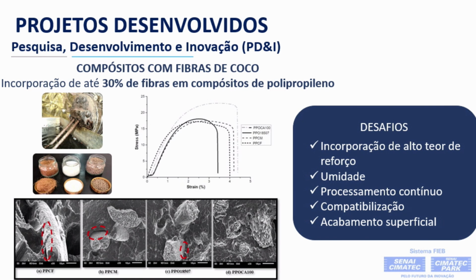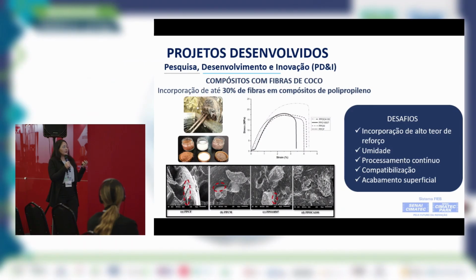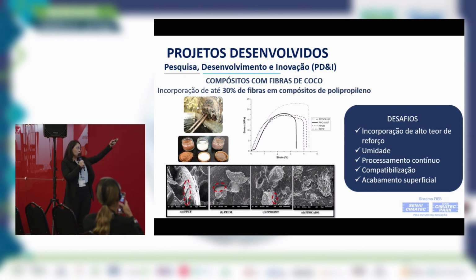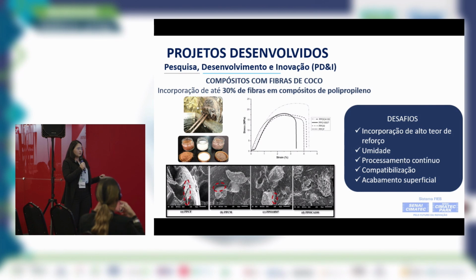Let me talk about the projects that have been developed at Senai Cimatec. The first one uses coconut fibers. So in this project, we incorporated 30% of fibers in a polypropylene matrix. So in this first image, we can see the material and the output of the extruder. And then the fiber was used in the polypropylene matrix, and then the pellets were obtained. The pellets were used for specimens, and they were tested. We have the microscopy and the tensile